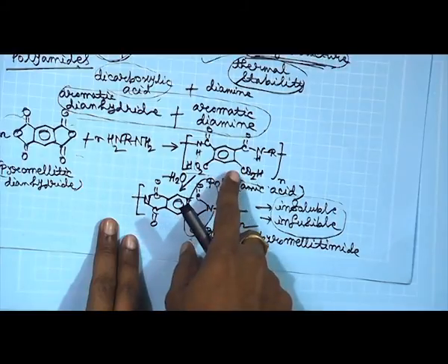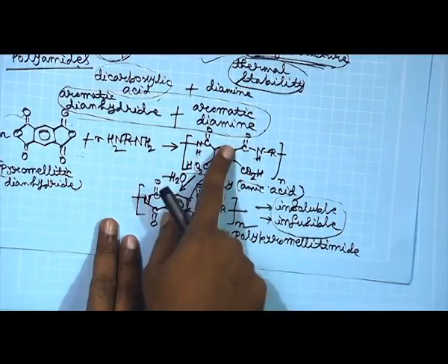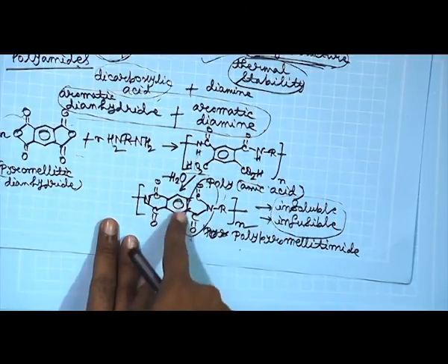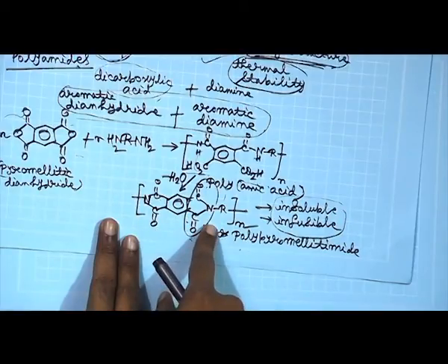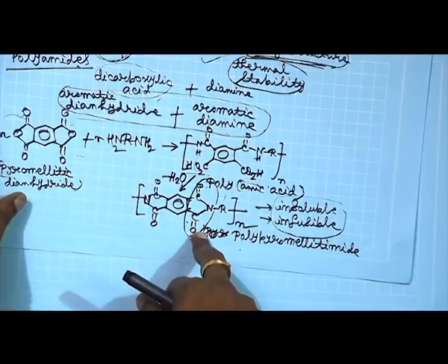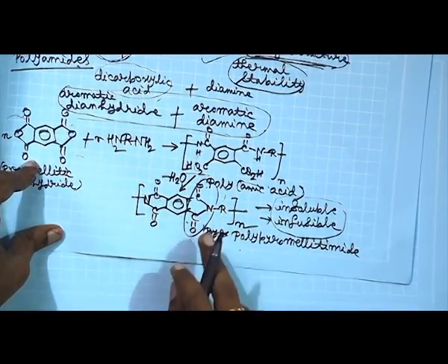But of course, one reason you now understand that you initially want to go to the desired molecular weight and then you cyclize, is because if you start to prepare imide from the start, from the starting point of the reaction, if you start to target that, then the problem is it will become insoluble, it will just come out before it can form a long chain. That is the problem.